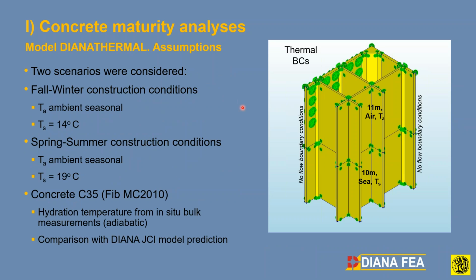given the situations. So what we did is we did two quarter models for thermal mechanical models, as we show here of the caisson. Portion of the caisson was inside the seawater, exposed to the temperature of the seawater, and then the outside portion was exposed to the variational daily temperatures of the season, depending whether this was a summer or a November, fall-winter kind of condition, like the figure case. So we had two different ambient conditions for the air temperatures, and the sea temperature was 19 degrees centigrade for the spring-summer construction schedule, and 14 degrees centigrade for the case of the failed caisson and what would happen during the winter construction of future caissons.